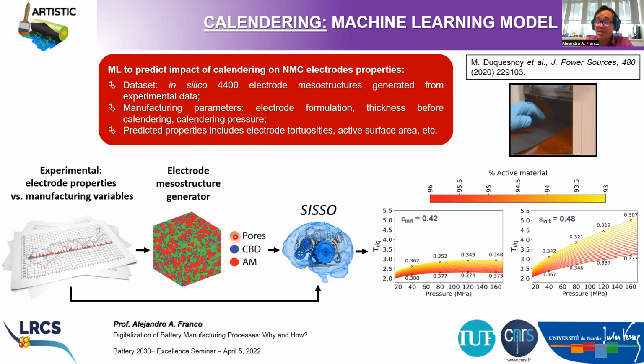And then we characterize these virtual microstructures in terms of a series of properties such as the tortuosity factor, the surface area of contact between active material and pore, which is supposed to be the active surface area, right? Because the pores are supposed here to be fully filled with the liquid electrolyte. And then we train with this data set a machine learning model that is able to perform regression predictions, right? And when I'm talking about regression, I'm talking about predicting numbers, right? And here you see a couple of examples of what you can get with this model. So you can predict the influence of the calendering pressure and the electrode formulation, and also the porosity before calendering, on the tortuosity factor of the electrode, okay?